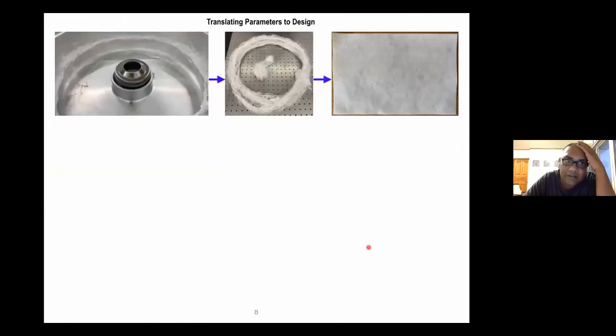So the basic process was, once the tinkering was done and I was able to generate the fibers in this cotton candy machine, you get something like this, fibers in this concentric geometry. I just sandwiched them between two glass plates that were lying around in my lab, and generated this fabric. If you look at my video, you'll probably see I'm holding one of those fabrics. These are slightly more dense than the commercial N95 electrocharged layer. We don't have that kind of quality control, but it was working fine.